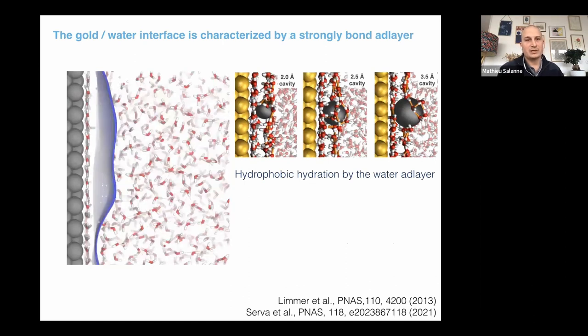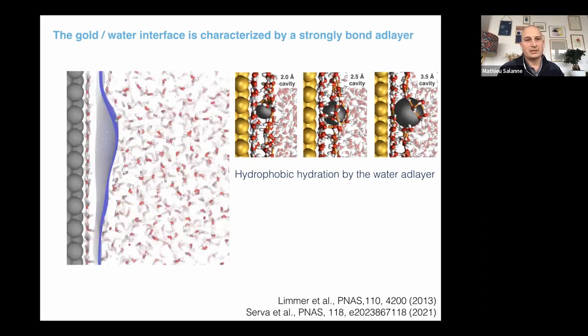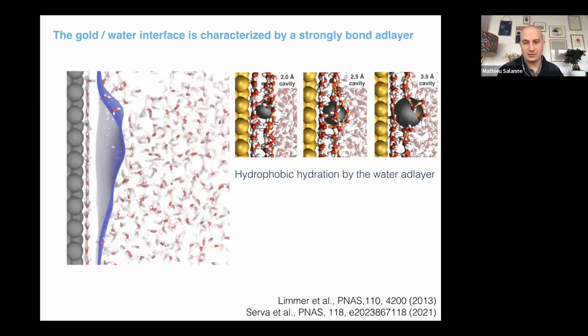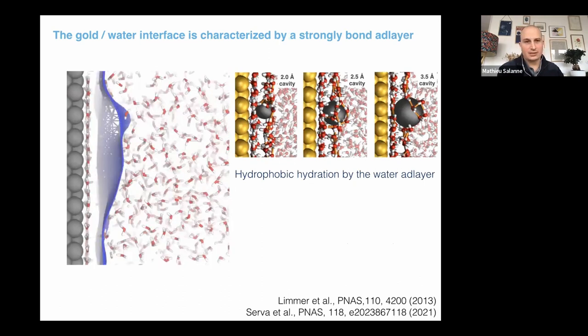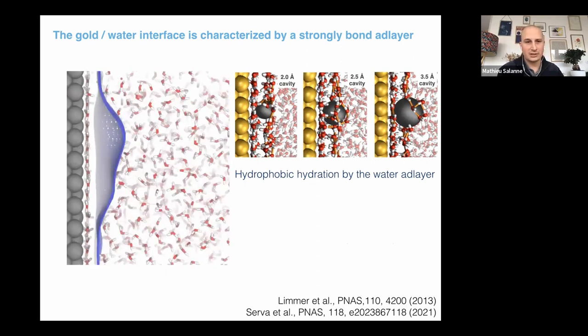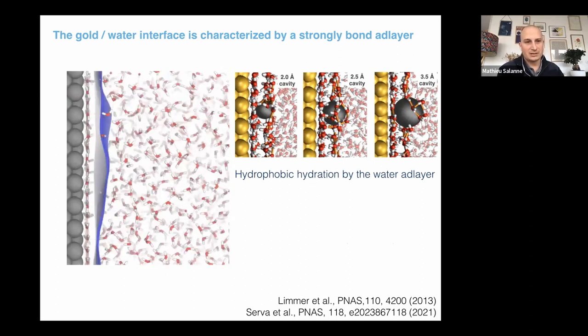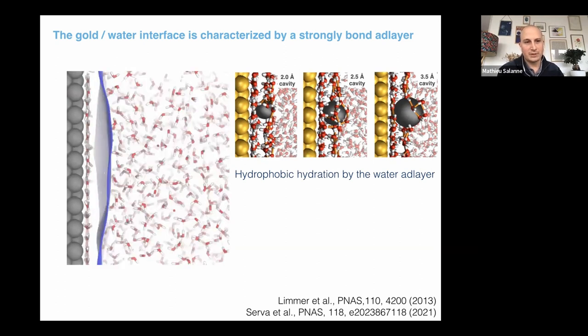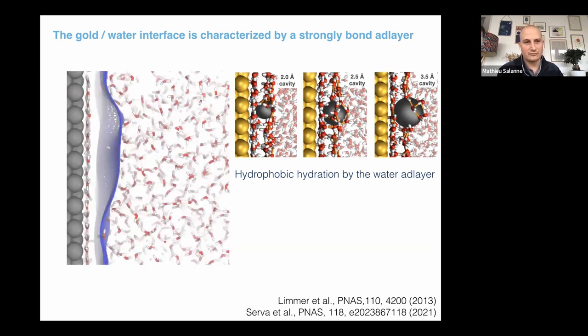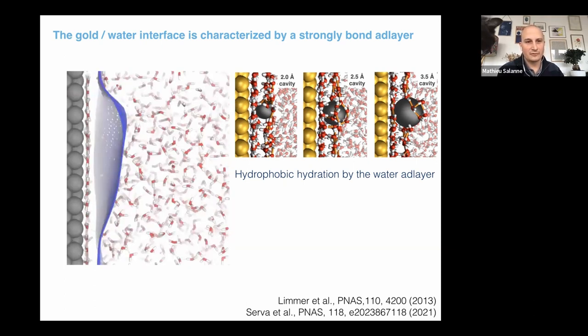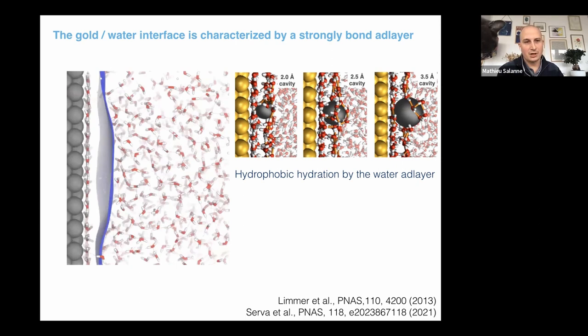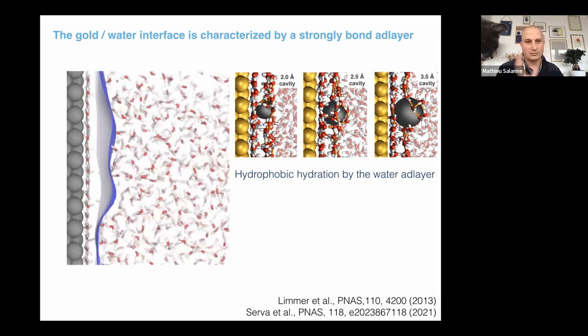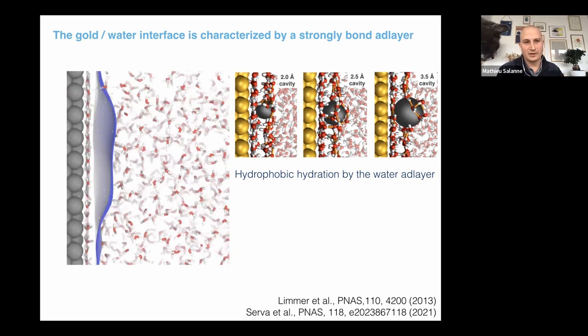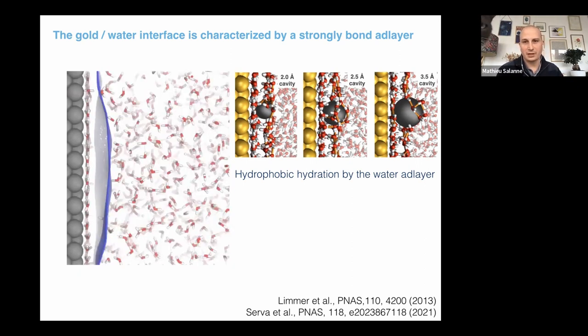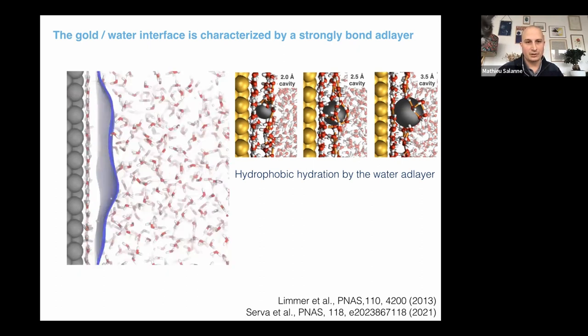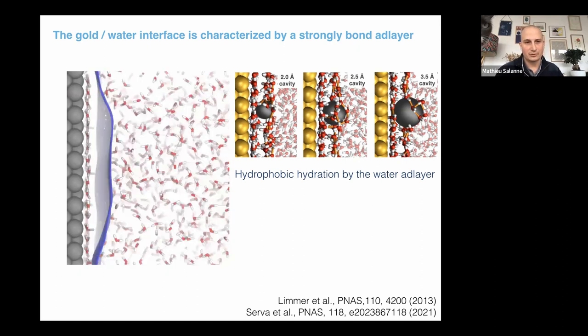Then we started to study more to go back to the gold water interface. So this is very recent, in the past 2 years. Here, that's a simulation from almost 10 years ago by David Limmer. And at that time, what he showed is that depending on the conditions and, of course, on your force field, you have this kind of fluctuation of the water adsorption. So you have a very strong adsorbed layer, and then you have a kind of liquid vapor interface, which is a bit hydrophobic and is fluctuating a lot on very short time scales.